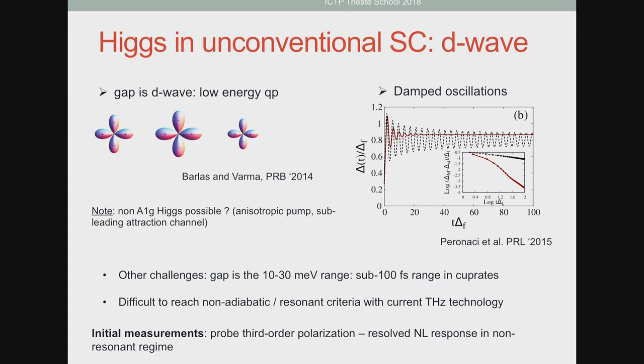Well, the first thing is that, as we discussed, in general, it's damped. And in the D-wave superconductor, it's even worse, because here we have plenty of low-energy excitations because there are nodes. So you would expect the damping to be even more dramatic than in the case of an S-wave. This was calculated by Peronaci and co-workers using a quench setup, similar to the setup I showed you before, essentially quenching the pairing interaction and seeing how it evolves.